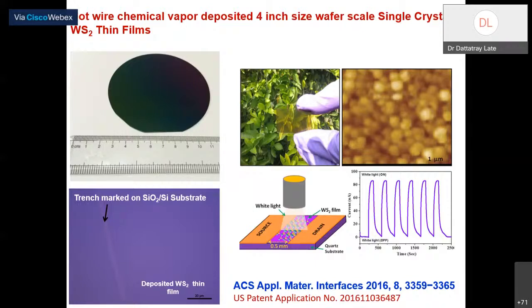So what happens now? This tungsten and sulfur gas molecular reaction will take place in the vacuum chamber, and I have the substrate kept at high temperature, and I will be able to grow a uniform film of WS2 or you can choose MoS2. So here I need a molybdenum wire or molybdenum electrode. The only thing you need is to evaporate that molybdenum wire or tungsten wire to grow these particular layers. So I have a uniform film of MoS2 or WS2, and this film is transparent in nature because again the thickness is very small. That's why it is much more transparent.